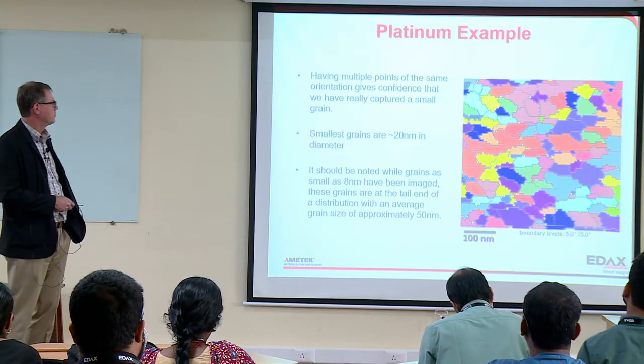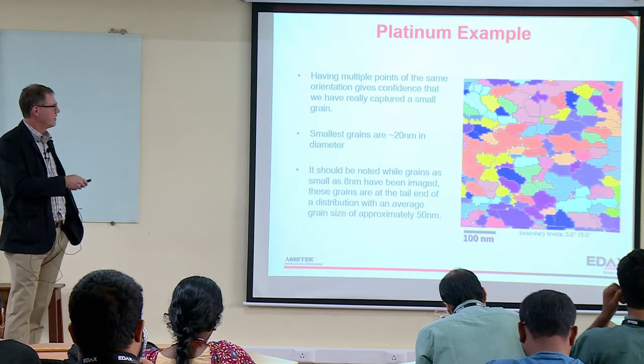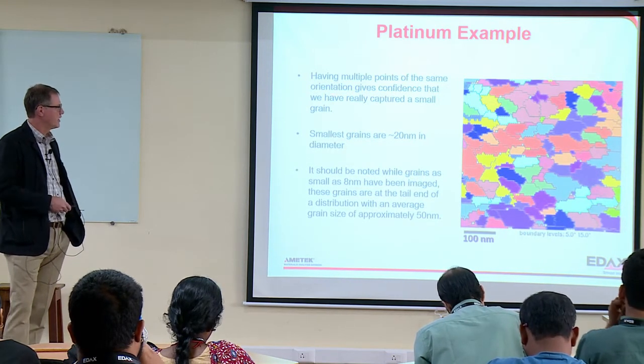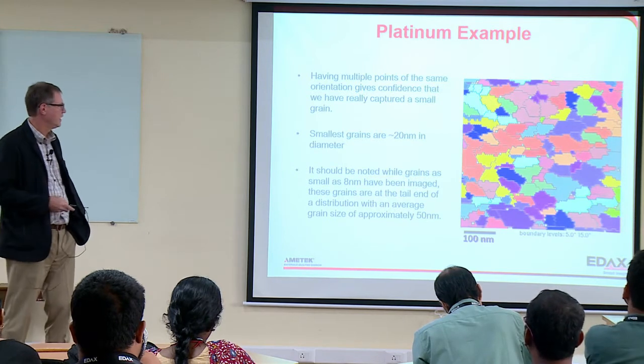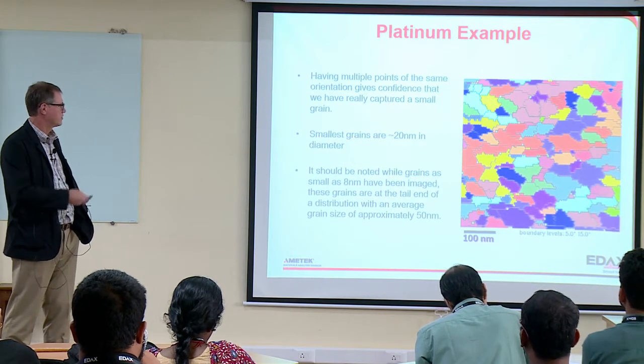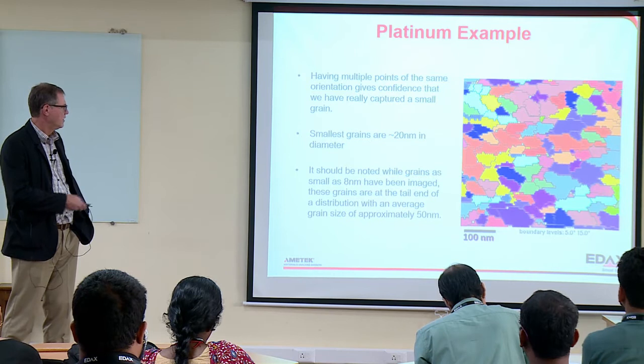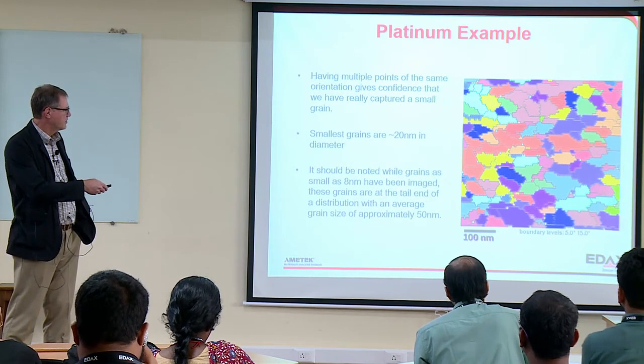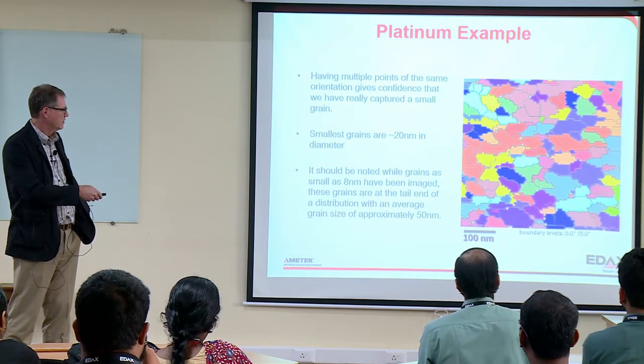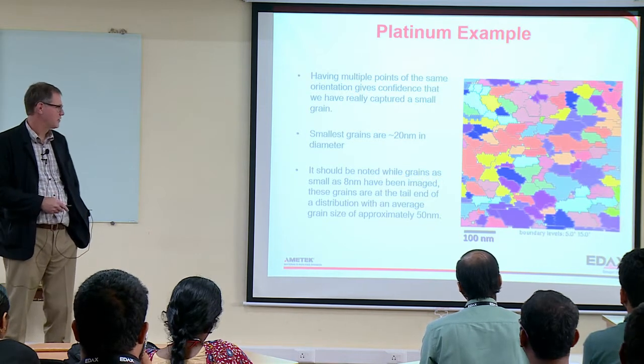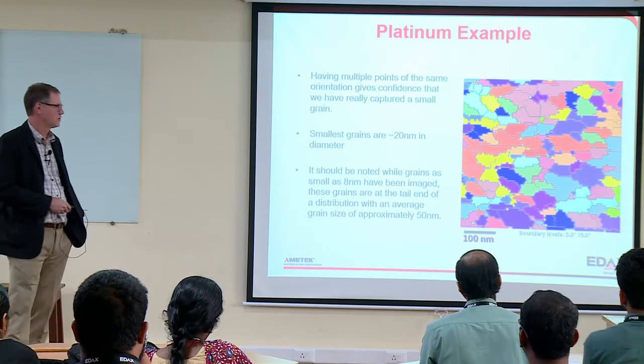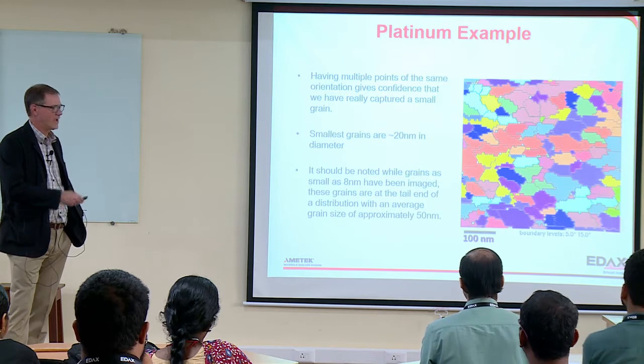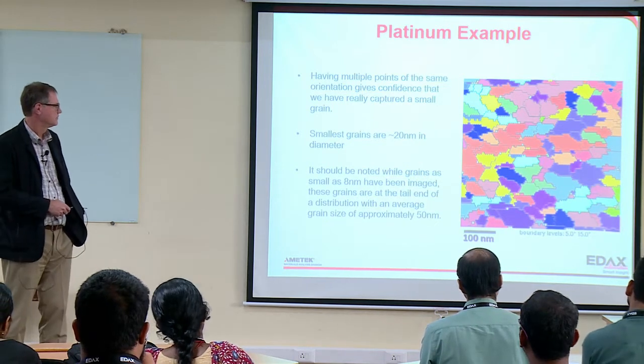Just to show you an example, we generally think we've got to have multiple points of the same orientation so that we know we've captured a grain. In this example, the smallest grains are about 20 nanometers in diameter. Now there are some that may be 8 nanometers, and I've made them white here. Those may be real grains, but it's hard to say. It's hard to trust those results, unless we go back in and look at the patterns for those.